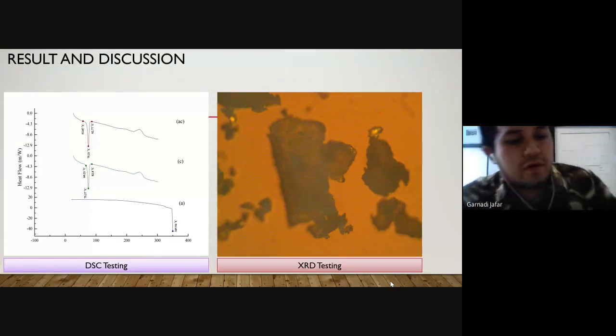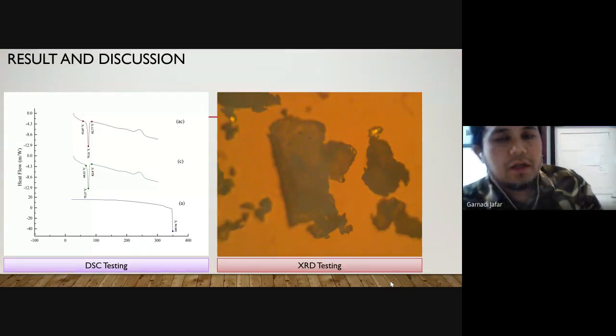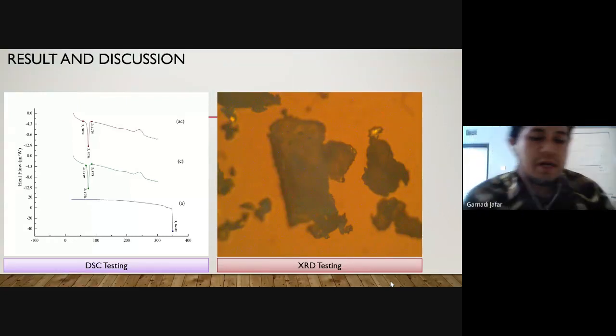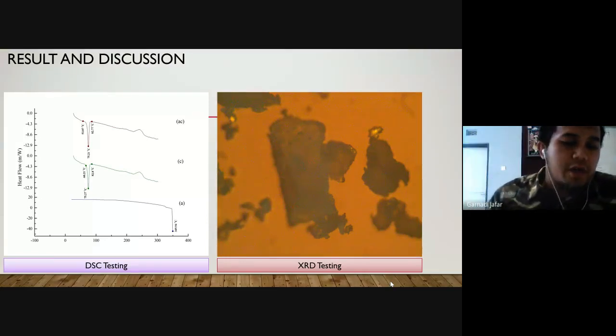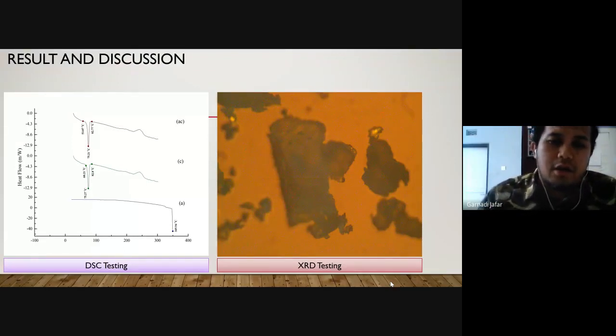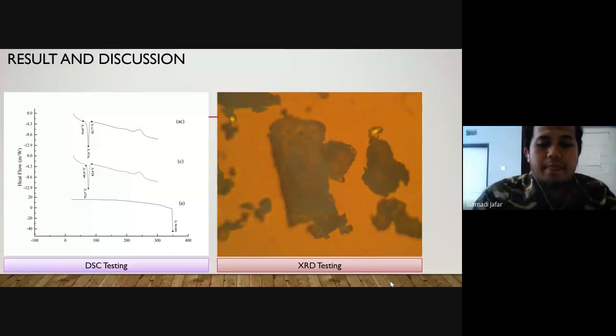The second image shows the melting point of Compritol at 82 degrees Celsius. In the third picture, the mix of adapalene and Compritol shows a decrease in the melting point of adapalene, following the melting point of Compritol. This shows that Compritol successfully encapsulated adapalene. And then, I'm sorry, not XRD testing, but the HSM testing. The HSM characterization proved that Compritol successfully encapsulated adapalene.